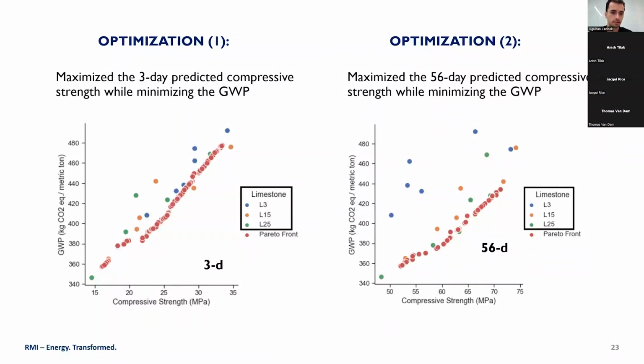So we optimized it in two ways. We said, let's maximize the 3-day predicted compressive strength while minimizing the global warming potential as much as possible. And in the second optimization routine, we maximize the 56-day predicted compressive strength while minimizing the global warming potential. These figures show global warming potential on the y-axis and compressive strength on the x-axis. The left one is 3-day, the right one is 56 days.